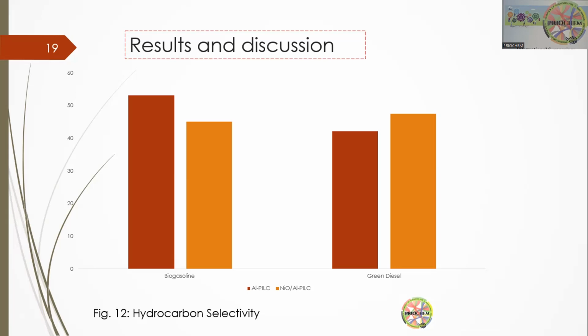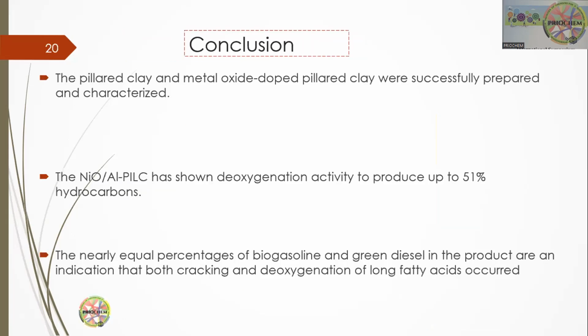So in conclusion, the pillared clay and the metal oxide doped pillared clay were successfully prepared and characterized. So the nickel doped on aluminum pillared clay has shown the deoxygenation activity to produce up to 51% hydrocarbons. And then the nearly equal percentage of biogasoline and green diesel in the product are indication that both cracking and the deoxygenation of long fatty acid are at play.